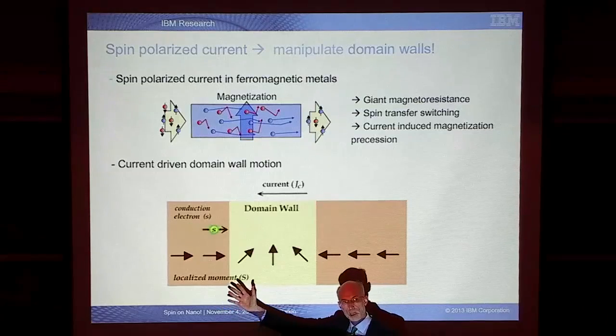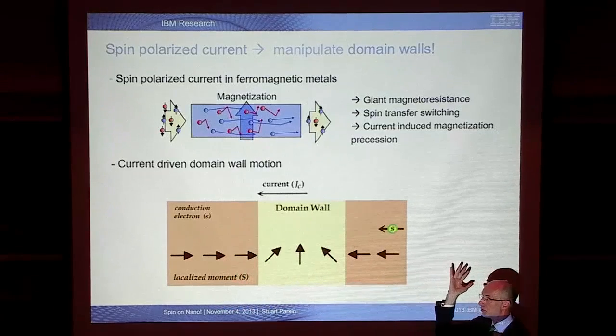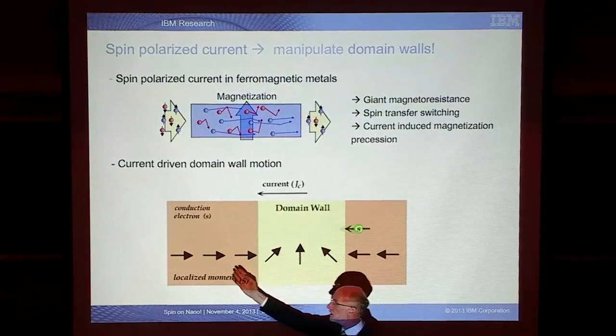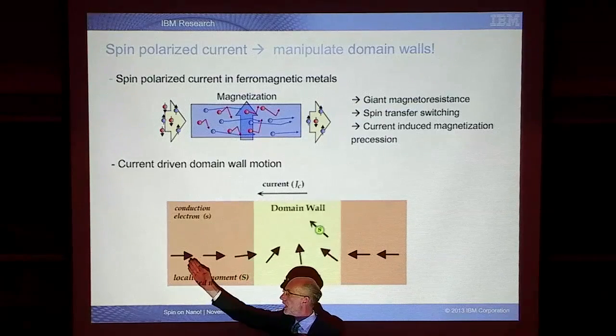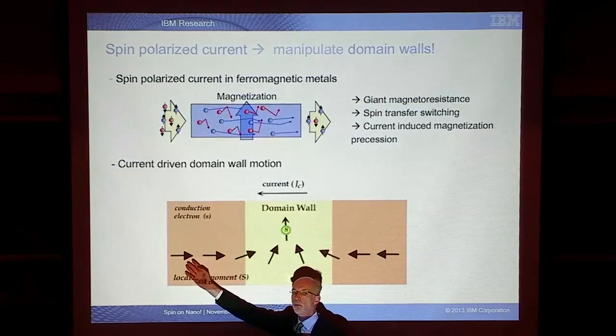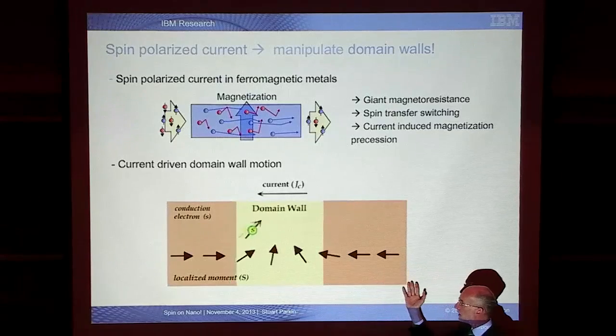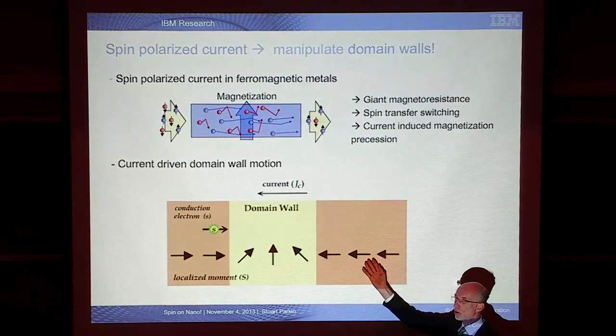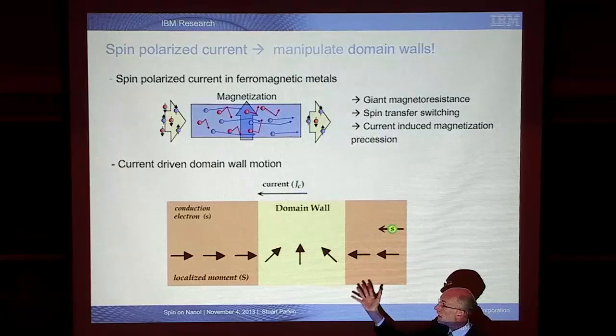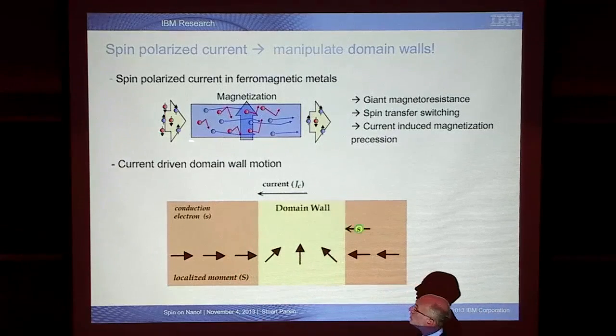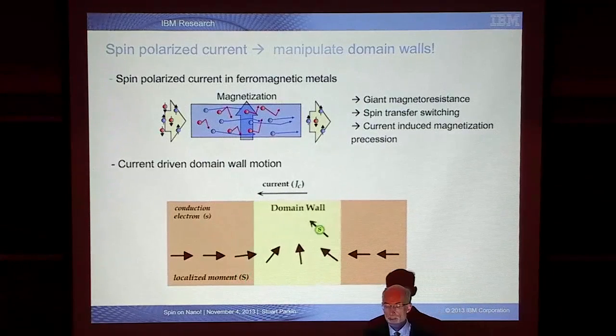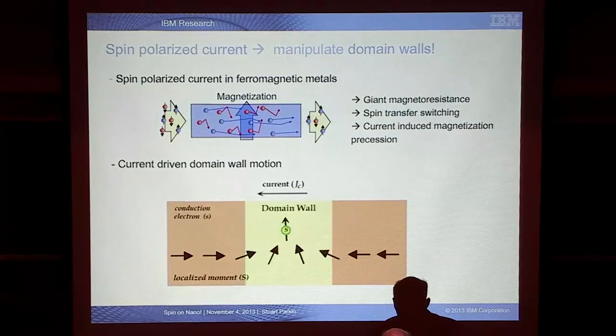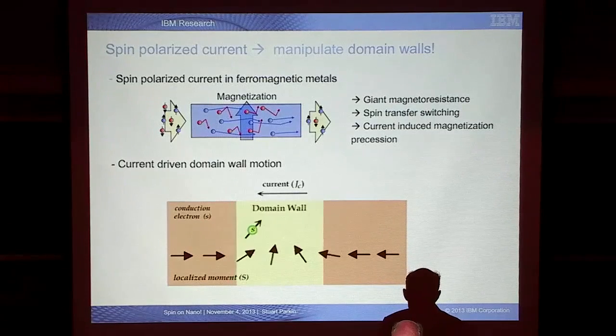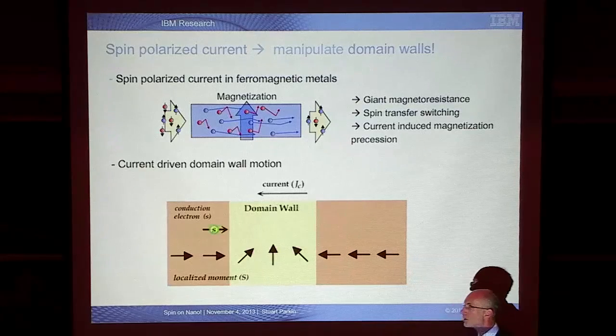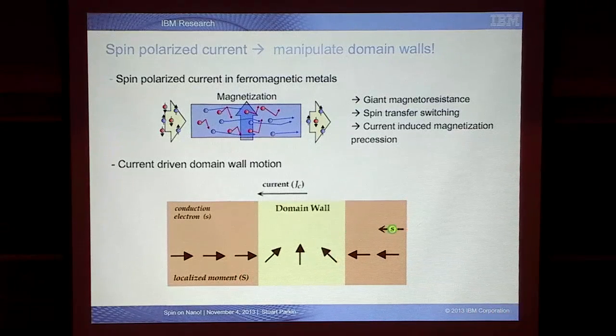So now let's take this. This is a cartoon of a homogeneous magnetic nanowire. On the left-hand side, you see the magnetic moments on the atoms have their moments all parallel to each other, pointing to your right. And on the right-hand side, the local magnetic moments on each atom are pointing to your left. In between, we have a boundary. This is called a domain wall. And this wall separating these regions of magnetization on the nanoscale has extremely interesting properties. These domain walls themselves are really topological objects which behave like an object of mass.